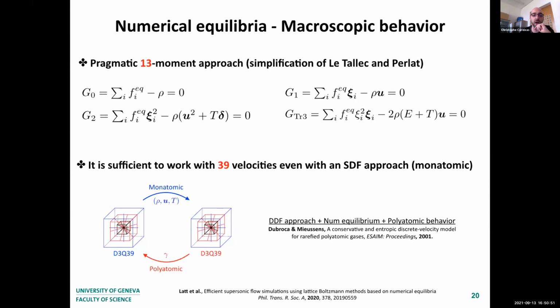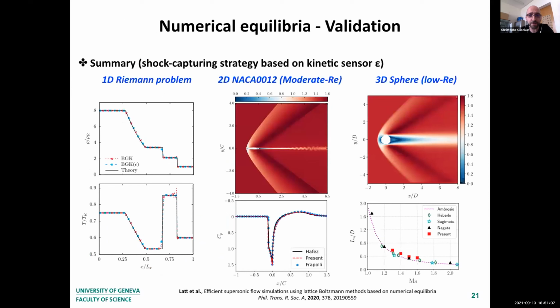And by further relying on the approach proposed by Dubroca and Mieussens in 2001, meaning using a second lattice in order to get the proper polyatomic behavior, then we are able to end up with a good trade-off in terms of efficiency, robustness, and accuracy. And in fact, this has been confirmed by simulating a 1D Riemann problem, the supersonic flow past a 2D NACA airfoil, as well as the supersonic flow past a 3D sphere.